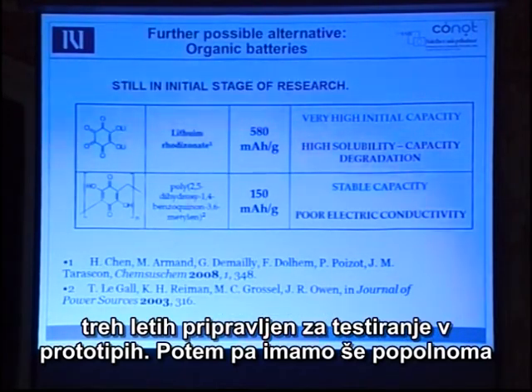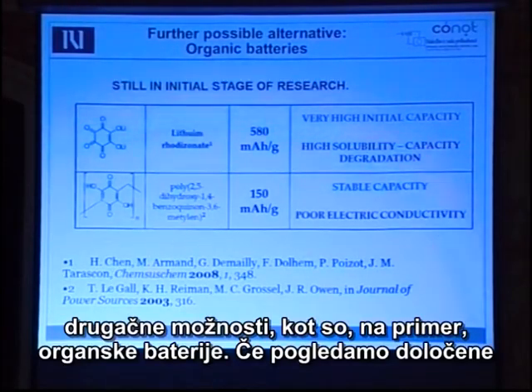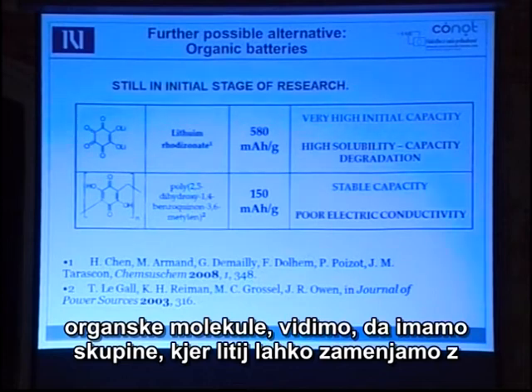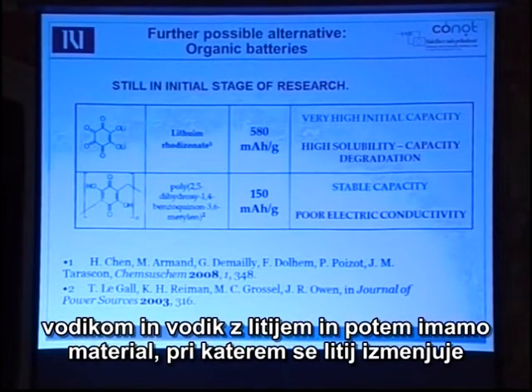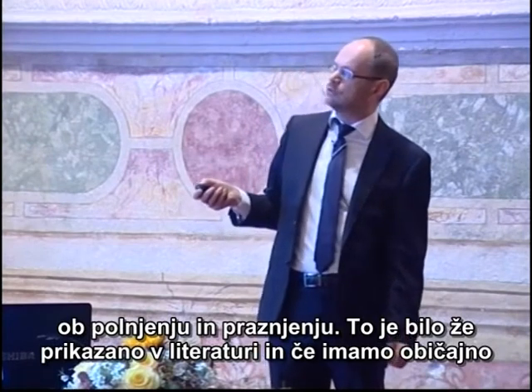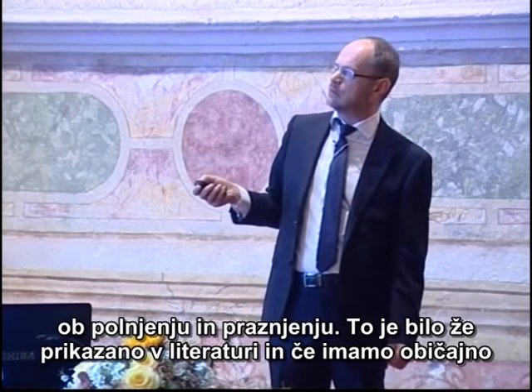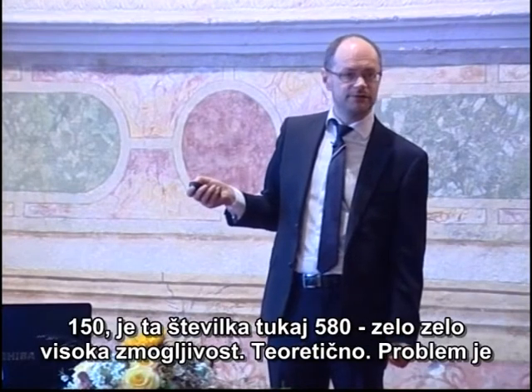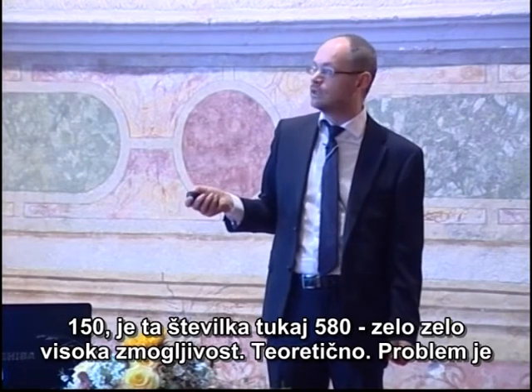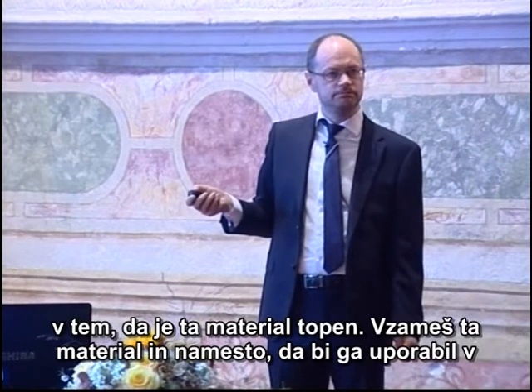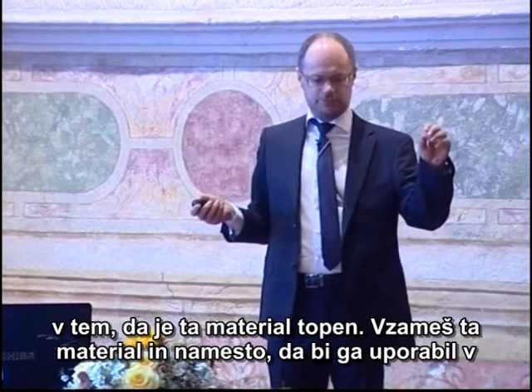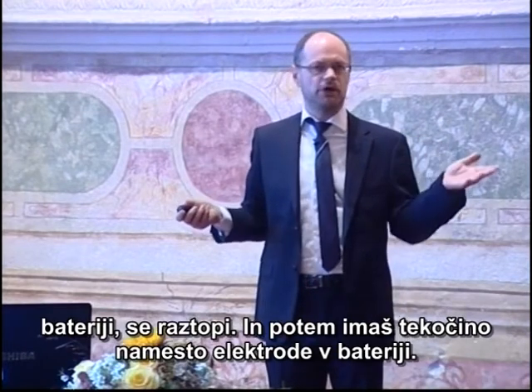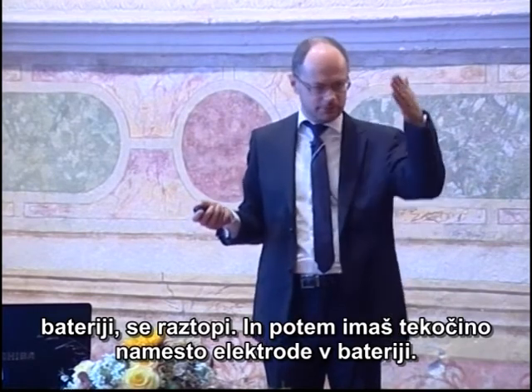Then there are completely other possibilities, like organic batteries. So if we look at certain organic molecules, we see that we have groups where lithium can be exchanged, for example, originally here is hydrogen, and you can exchange hydrogen with lithium. And then you have material where you can exchange lithium during charge and discharge. This has been shown in the literature. And if we have usually number 150, this number here is 580. Very, very high capacity, theoretically. The problem is that, for example, this material is soluble. So you take this material, instead of using it in a battery, it dissolves. So you have a liquid instead of a battery electrode.